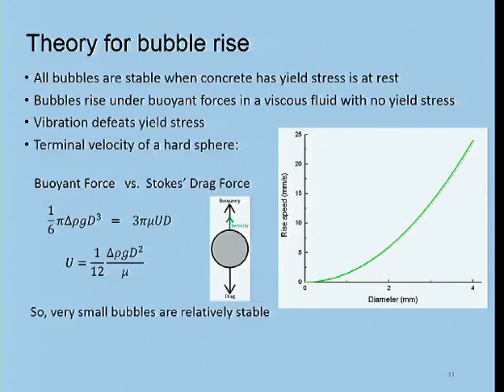The equations we get from this analysis of the buoyant force versus Stokes' drag force lead us to understand that small bubbles are resisted by the viscosity of the fluid, and the smallest bubbles are the slowest in their movement. So the velocity of the bubbles, U, is going to be highest when the diameter of the bubbles is high. And so we get a picture here that under vibration, the first things that are going to leave the system are the largest voids. They will tend to escape quite quickly. The very, very finest voids have some stability by nature of the viscosity of the system.